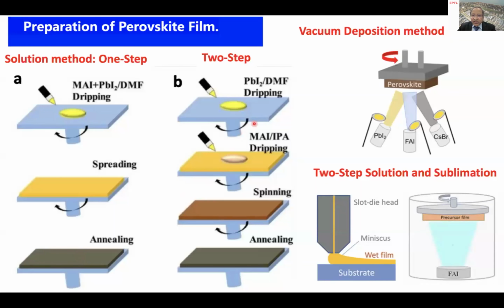And the second one is the two-step method, where first we deposit lead iodide, followed by exposure to the organic halide compound, which gives the perovskite, sintering at 120 degrees temperature. The third one is most important for tandem configuration applications, where you deposit the perovskite on top of a silicon substrate by incorporating different crucibles with lead iodide and your organic halide cations. You sublime this under vacuum, and in the gas phase you form the perovskite film.